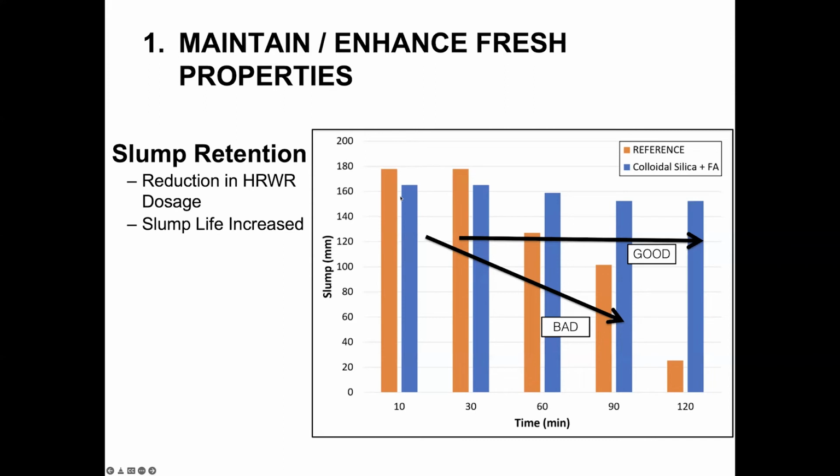That is one of the things that I was concerned about environmentally, because if cement in designs were going to go down in quantity as a consequence of greenhouse gas emissions, then the greener the concrete was going to get, inevitably it meant less paste for us, which meant harder pumping. But with internal cure, when you see that reduction in pumping pressure, it leaves that room to reduce your cement content a little bit without sacrificing either performance or workability in terms of pumping. And the workability flows right down the line to placement.